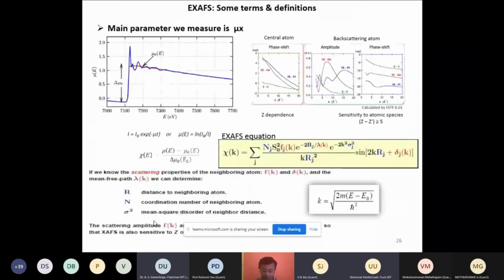So there are some terms and definitions in EXAFS used for analysis of the structural parameters. This is the raw data obtained from the transmission absorption curve, and this is mu(E), which is derived by Beer-Lambert's law, and then you see the oscillations. But mind you, although this oscillation should look like a sine wave, it is not really a sine wave, although you see the sine term here.